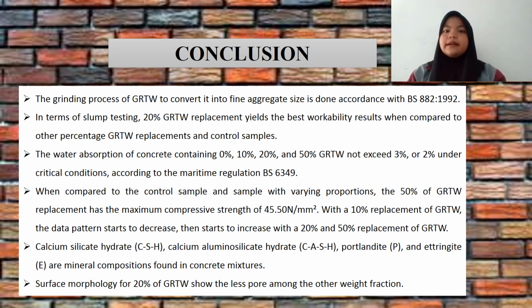In conclusion, the grinding process of GRTW as a fine aggregate is done in accordance with the BS standard. In terms of slump testing, 20% GRTW yields the best workability result when compared to other percentages of GRTW and the control sample. The water absorption of concrete containing 0%, 10%, 20% and 50% GRTW does not exceed 3%, or 2% under critical condition, according to the marine regulation BS standard.